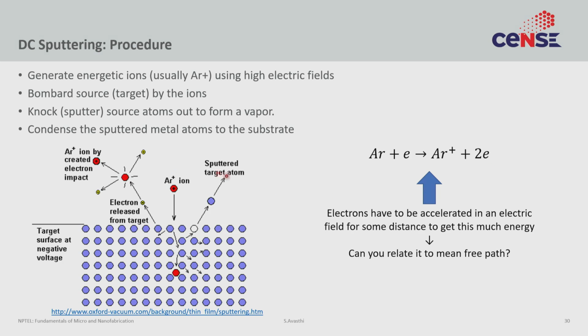And once you have these argon plus ions, you already have the electric field. The argon plus ions react to that electric field and come bombarding on the surface, very much like ion implantation, though the energies here are much, much lower than ion implantation. And then those argon atoms knock the structure of the lattice, causing every now and then some atom to get sputtered out, right? So that's the basic idea.